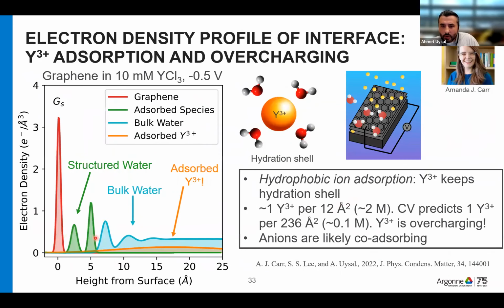And the results we are getting are very, very interesting. Number one, most of the structuring that we see is not directly related to the yttrium. The yttrium distribution is shown with this orange line, and it is a very diffuse profile, unlike most of the adsorption that is observed at mineral-water interfaces. By the way, we do this in collaboration with Sang Soo Lee in Paul Fenter's group, and they have been studying mineral interfaces for a long time. And this is very different compared to what you observe on a typical mineral surface.